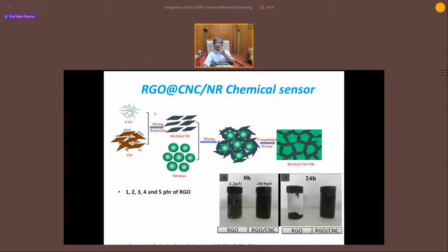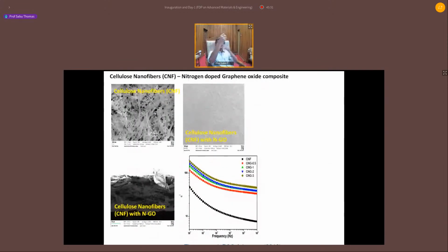Let me now show you the energy storage application. A PhD student of mine made nanocellulose, and then he made a hybrid structure. Nanofibers mixed with graphene oxide. We found that this is a fantastic material for energy storage. This is nanocellulose alone, and this is varying concentration of nitrogen-doped graphene oxide. You see the dielectric constant increases dramatically. That implies this is a fantastic material for energy storage. So hybrid construction is always excellent. You get fantastic properties.